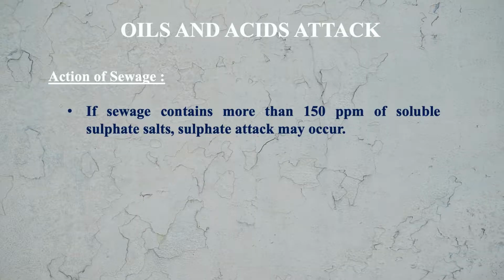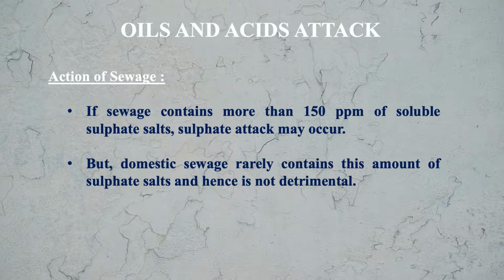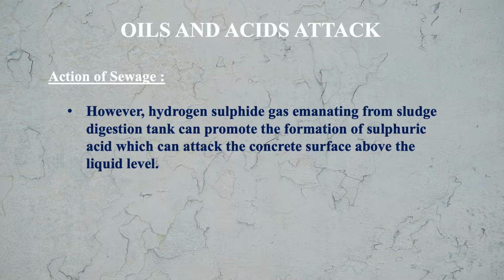Let us see the action of sewage on concrete. If sewage contains more than 150 ppm of soluble sulfate salts, sulfate attack may occur. But domestic sewage rarely contains this amount of sulfate salts and hence is not detrimental. However, hydrogen sulfide gas emanating from sludge digestion tanks can promote the formation of sulfuric acid, which can attack the concrete surface above the liquid level. So the concrete above the liquid level can be affected by this sulfuric acid, which will be formed in the sludge digestion tanks.